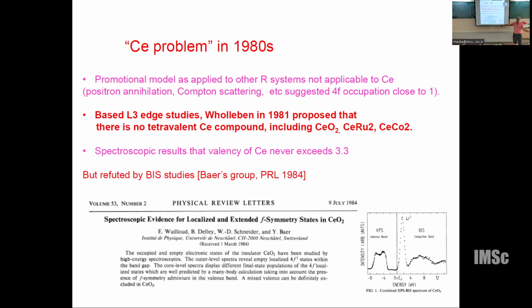When the transition takes place, the oxygen emission goes up. So that way he has proved that there is a 4f symmetry in the oxygen band. You follow what I mean? Originally I said 4f electrons are localized. Now you find the 4f electrons sitting in the oxygen band, where the bonding takes place. So that means the 4f can participate in bonding.